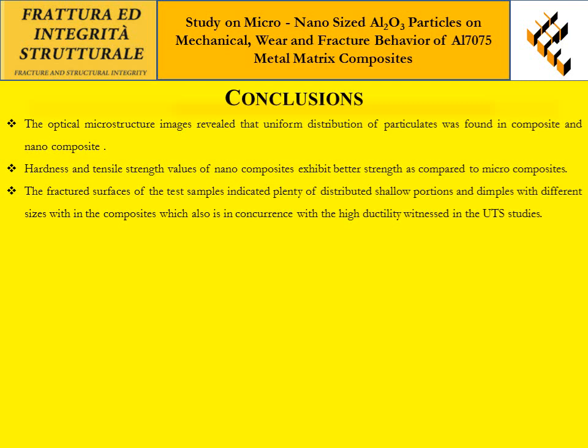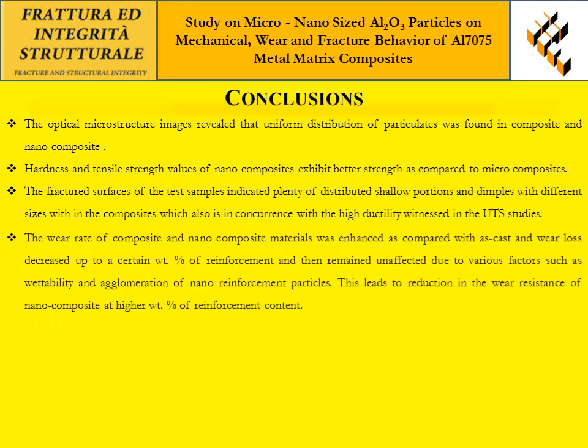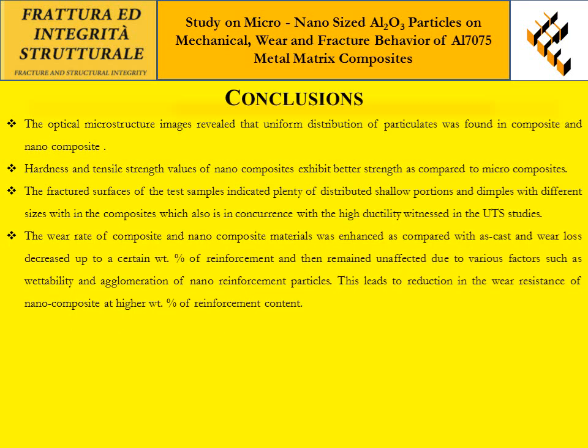Conclusions. Microstructure reveals the uniform distribution of Al2O3 particulates within the composites and nanocomposites. Hardness and tensile strength values of nanocomposites show better strength compared to microcomposites. From the fracture surface, it is revealed that high ductility was witnessed in the UTS studies. The wear resistance of nanocomposites was found to be better when compared to the microcomposites.